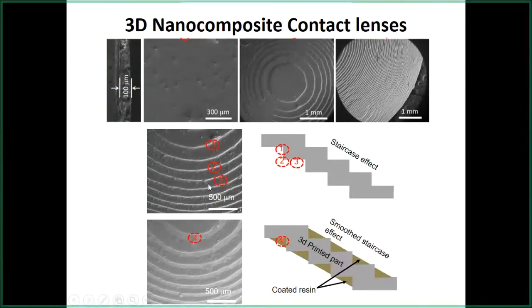So what we did was, we have optimized the curing process itself. Our printers allowed us to actually play with the layering parameters: how fast each layer should be printed and how fast it should be moved up. One of the things was that we also added one extra step post-printing. After printing our contact lenses, we dipped them again one more time in the resin, and then we cured them. So then what happened was that these staircases were actually filled with the hydrogel. If the hydrogel is viscous enough, it sticks over here, and then you can cure it again. So it sort of gets rid of this staircase effect, and the surface becomes more uniform.